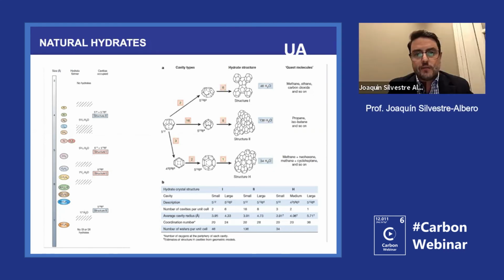Yeah, in principle, if you have oxygen surface groups, you will modify the interaction of the water molecules with the surface, and then you will change completely the growing of this hydrate. No? We only did some experiments a few years ago, but I'm not really confident. We only did some trials to see the effect of oxygen surface groups, and of course we observed that you cannot get the same water-to-hydrate yield. Because when you put oxygen surface groups, you are changing the interaction of the water molecules with the surface. So in principle, having oxygen surface groups is not very convenient if you want to make these gas hydrates.